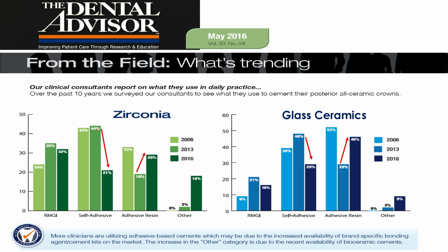As mentioned in the article by Gordon Christensen, the surface treatment of the prosthesis plays a major role. Then the question arises, when the surface treatment of the prosthesis as well as of the tooth plays a major role, why not use an adhesive resin cement, which provides much more reliable and much faster bond strength when compared to the self-adhesive resin cements? So it's always better. That's the reason you can see in this survey, in the last 10 years, the use of adhesive resin cements has grown multifold, and the use of self-adhesive resin cements, both in the case of zirconia as well as glass ceramics, has come down.